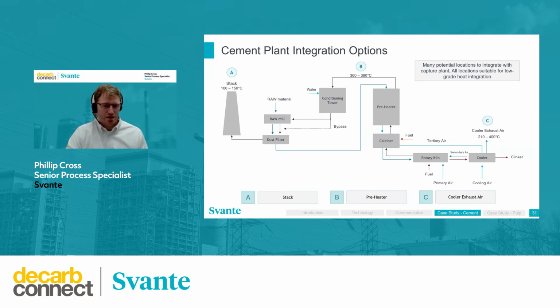Some of the cons are, however, that the CO2 concentration can be lower due to possible false air making its way into the stream. You're subject to variations in flue gas during switching between modes of operation. I'll cover a little bit more of that in a second. And for cement plants, you also have relatively low gas temperature as well as CO2 compared to other tie-in locations, such as location B.